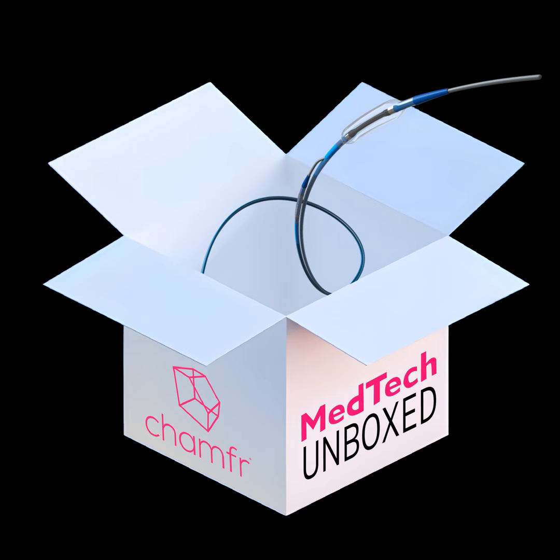Very interesting, because we've seen the massive growth of laser cut hypotube for reinforcement in some of these modern catheters, especially steerable catheters, transseptal, electrophysiology, structural heart type applications, where there are higher deployment forces. But one of the challenges is that you're reflowing the material within the kerfs of the laser cut patterns, which affects flexibility. So this is kind of where you're headed with that, right? You're not necessarily loading those kerfs with a material to bind it up. And if you do, it's with a super low durometer material.